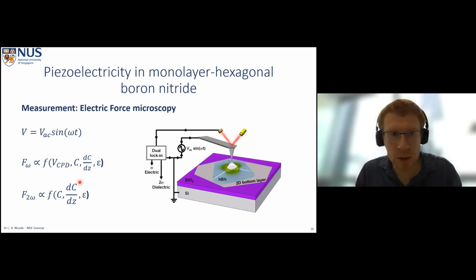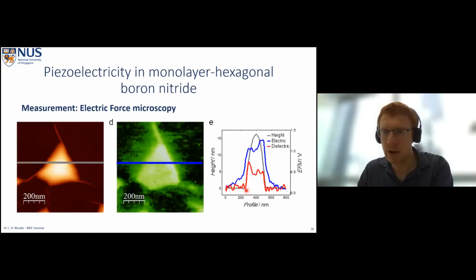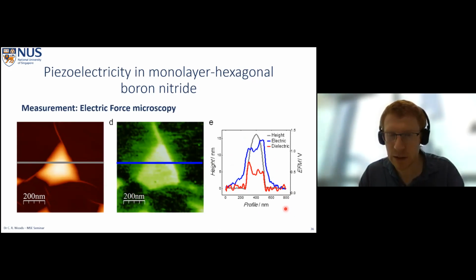So what we can say is, if we see something in the first harmonic and not the second harmonic, we know that this is due to the potential difference from the tip to the silicon. This allows us to take out, say, capacitance and dielectric changes. When we look at our profiles, the red curve here, the second harmonic, drops to 0 just as the topography drops to 0. But the first harmonic stretches hundreds of nanometers into the stack, way beyond our measurement resolution. And so we can say that this is due to the potential difference.